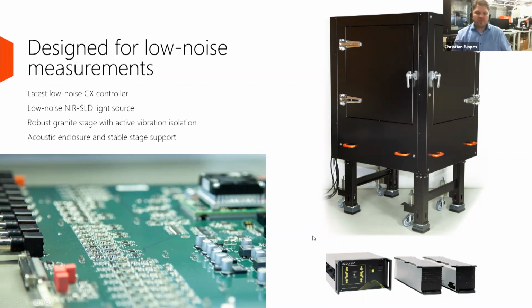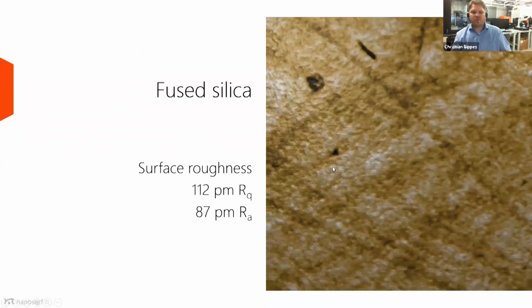Okay, so examples. There is an image, for example, here of a fused silica glass surface, which has a roughness of around 112 picometer RMS or RQ. And if you look at the RA value, that corresponds to 87 picometers, which is quite a smooth surface already.